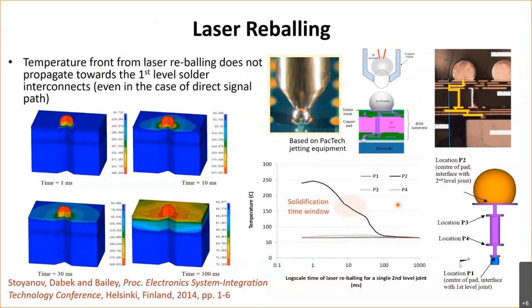for deballing. And then we have laser reballing. So this is a sort of PacTech process where we'll actually place new balls on those pads. And here we could see how the temperatures again change. And as a liquid ball is placed on the pad, we could see how the temperature decreases over time, again at the same locations. Not a great change to the first level solder joint.